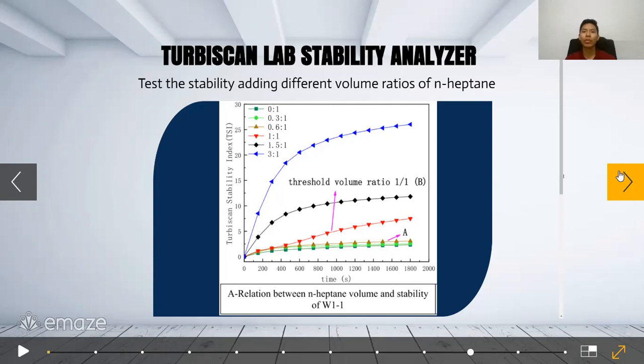In this method, first, the crude oil is placed in a sample cell at a stable temperature. It was around 25 Celsius. And the apparatus emitted a light that passes through the cell, and in the next phase, a certain amount of n-heptane is titrated with the crude oil. There were used volume ratios of 0:1, 0.3:1, 0.6:1, 1:1, 1.5:1, and 3:1. In the volume ratio of 3.1, it's where the precipitate showed.